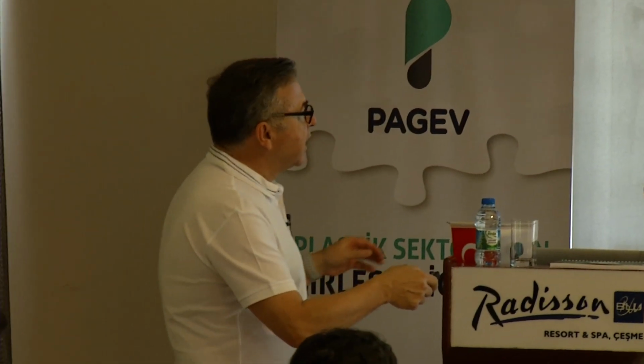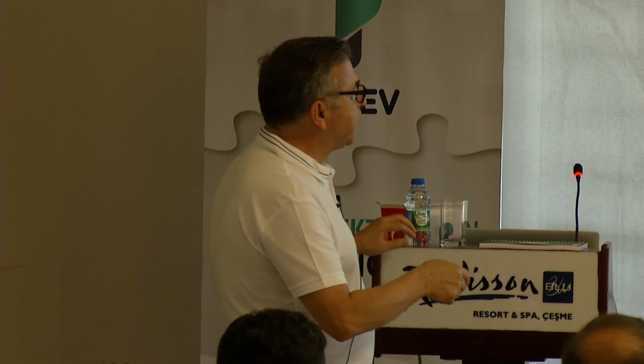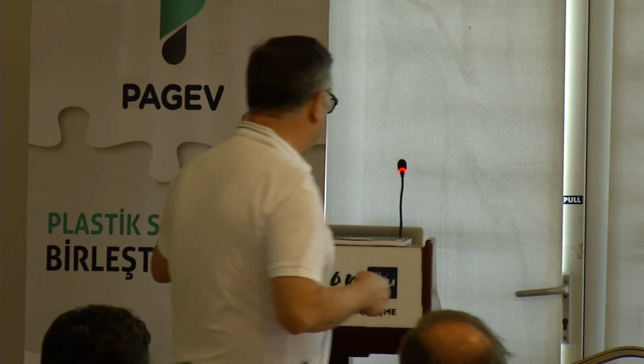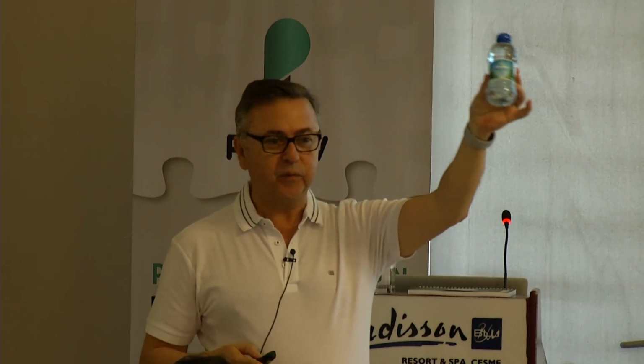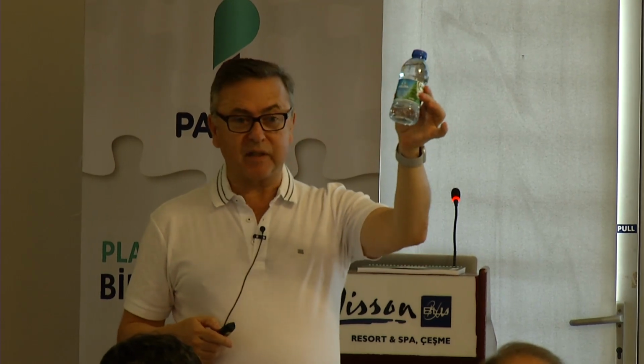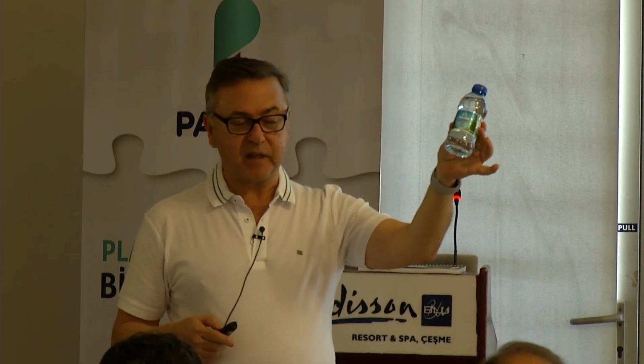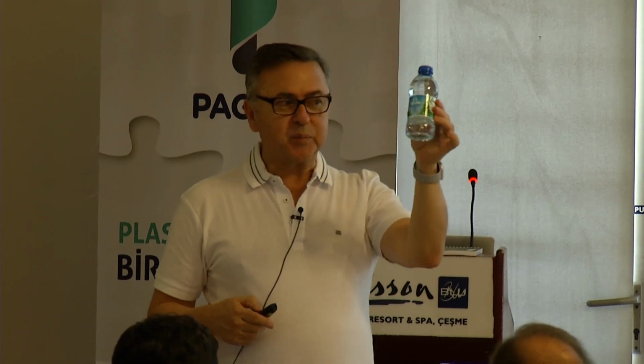So if you have a regular chain, you can quench it into an amorphous state, and this is a dominant factor for making this polyester bottle. To make the polyester bottle, you injection mold a preform, right? It's a tube. Many of you, I don't know if any company makes these things in Turkey, in the crowd. And you make it literally amorphous because the glass transition temperature of PET is 85 degrees centigrade, 80 degrees or so. So you take this, injection mold it, and the material is completely amorphous.